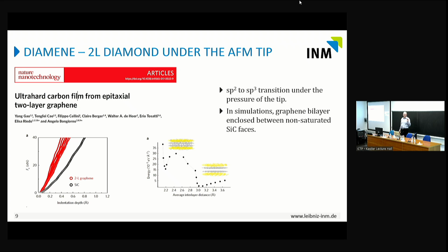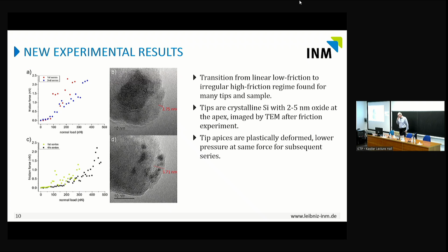What we thought was, this is probably our friction. We are sliding with the tip over the surface, we increase the load, and suddenly we need a lot of energy to produce diamond, which we will never get back, because we are sliding already, we moved on before the diamond pops back into sp2. This was our idea, and we tried to simulate this, and it turned out it doesn't work. Let me first show you a few new results.